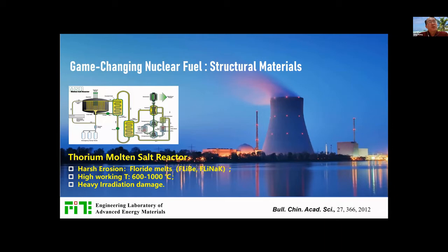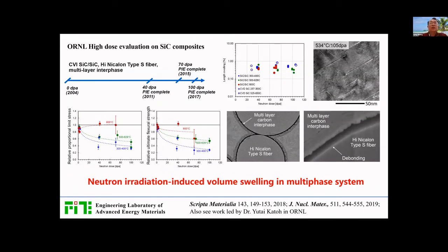Here is an example. In the 4th generation reactors, there is a thorium molten salt reactor. You will see that it works at very high temperature, around 600 to 1000 centigrade, much higher than the normal working temperature of reactors. And more especially, it will use fluoride melt, so the erosion of the structural alloy will be very hard. So that's the reason we should find suitable structural materials for the next generation reactors.